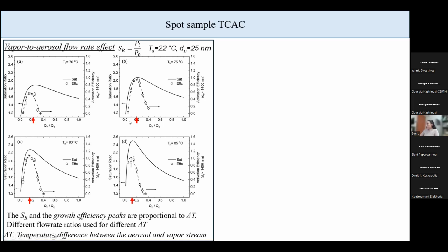Now, another thing that we notice: the dashed line and the points represent the experimental activation efficiency of 25 nanometer particles up to sizes greater than 1.4 micrometers. In all cases, we see that we have at least some partial activation growth, like in the first case at 70 degrees Celsius. In higher water temperatures, we can achieve complete activation efficiency.